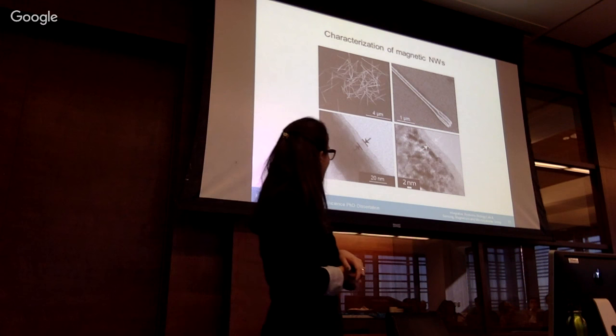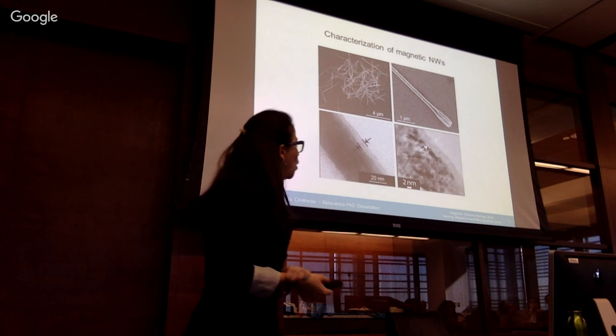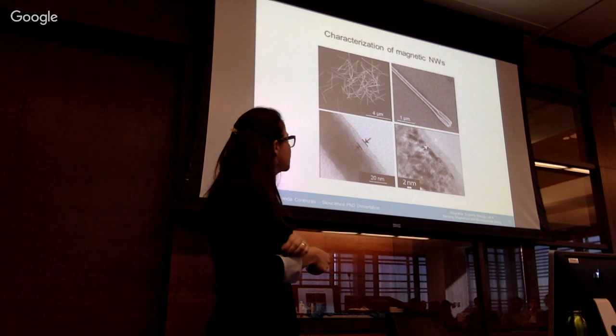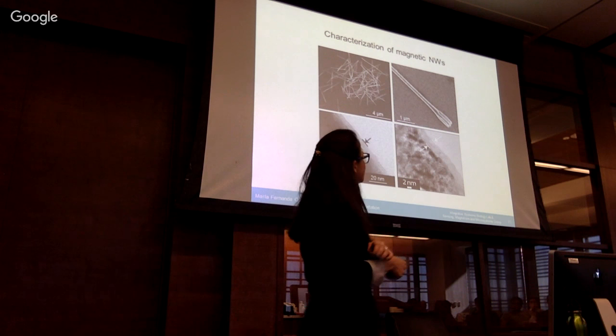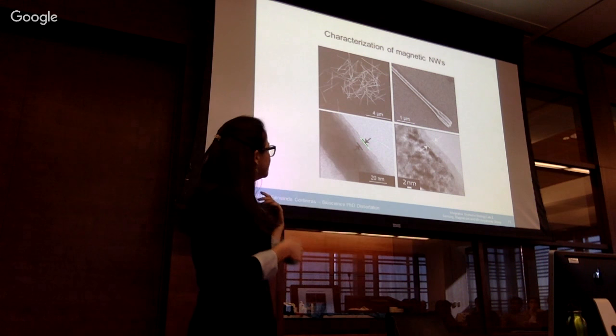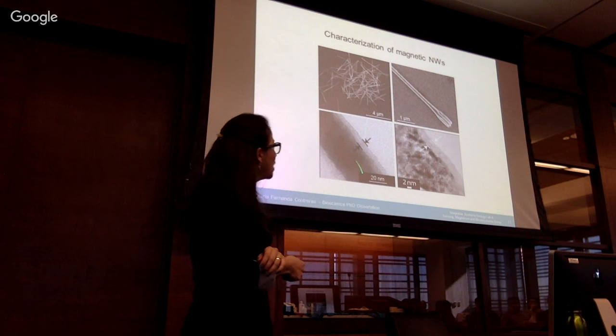And these bottom two highlight the naturally occurring oxide layer of the wires. When we expose them to different solutions, they do grow this oxide layer in both nickel and iron. This image is a high resolution TEM, so each one of the dots here is an atom. I did composition analysis of this, and I found out that there you can only find oxygen and the corresponding metallic material. So you do have a nickel oxide here and a type of iron oxide on your iron nanowire.